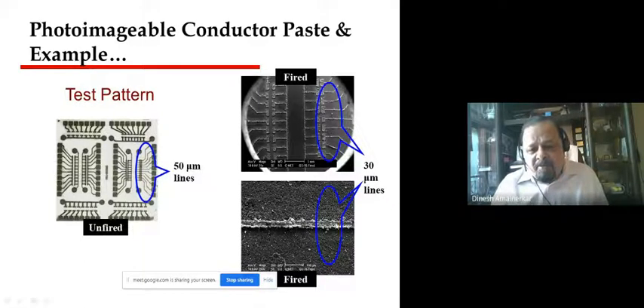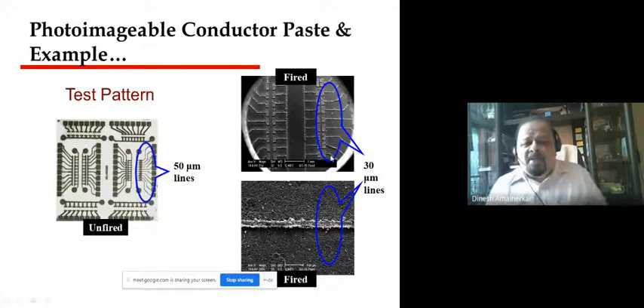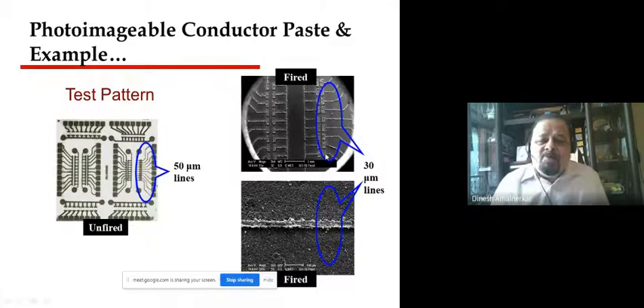But if you have a higher resolution SEM image here, probably you can see there is some problem with the edges. And we feel that to get the 30 micron lines, we can't use micron size silver as the starting material. Definitely, you need a lot of nanotechnology related synthesis techniques to generate nanoscale silver, which can be suited for this particular application to avoid this kind of problem at the edges.